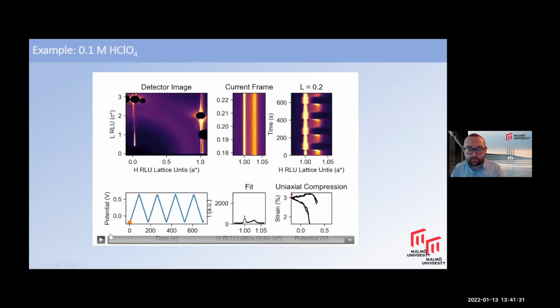Another example, just to quickly show you, we did this in perchloric acid, and so here the reconstruction actually lifts at a much lower potential. They're both against reversible hydrogen electrodes, so they're corrected for the pH. In this case, you can see that we can repeatedly lift the surface, and it recovers quite nicely, which isn't the case with methanol.